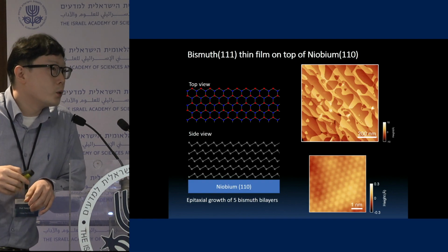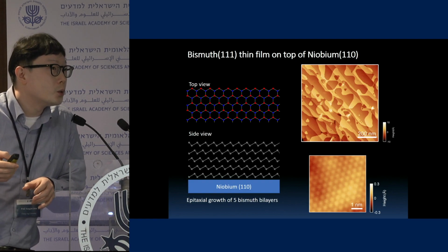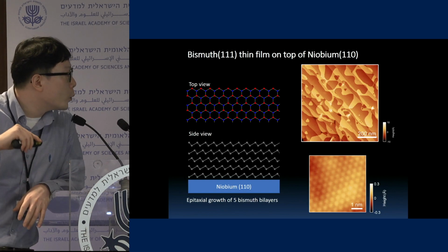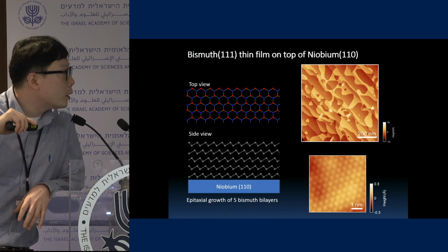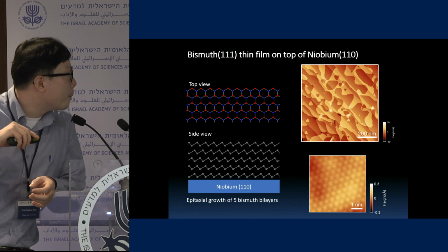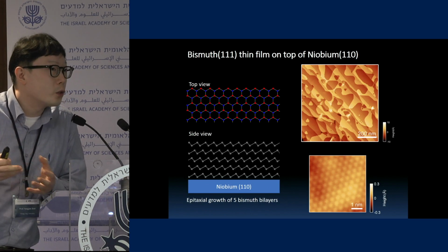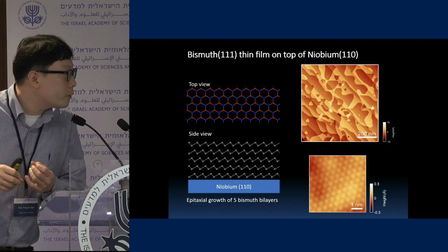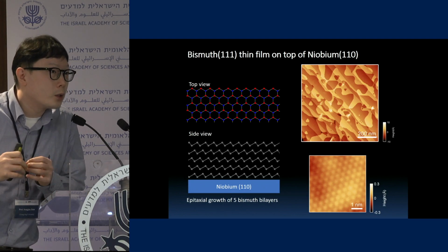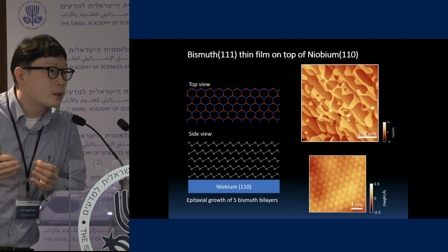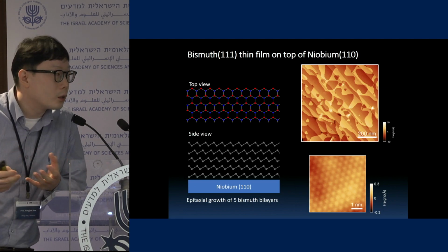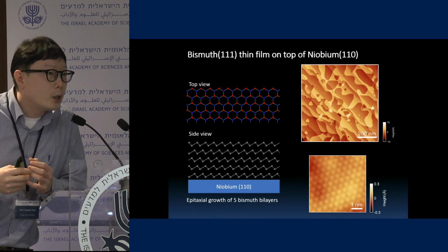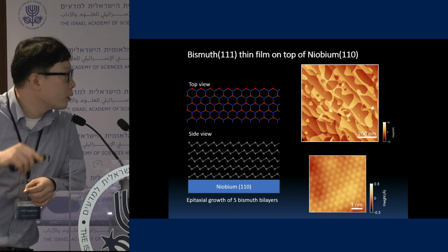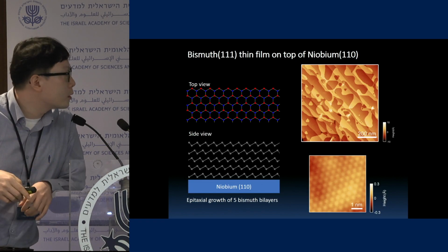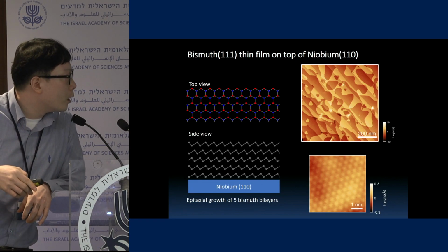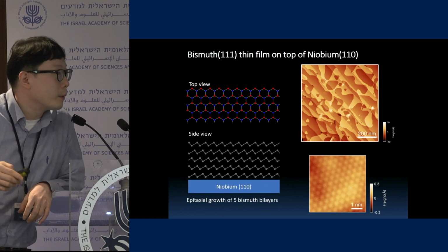So we decided to induce superconductivity in these bismuth systems. We used niobium as a substrate, and we made a thin film of bismuth on it. Actually, we use 4 to 5 layers of bismuth. The reason is that if it is too thin, then it will not grow in one direction, so it will not give us this kind of special edge states. If it is too thick, then it will not get strong enough superconductivity from the niobium. So in our experience, 4 to 5 layers give us a good system to understand the Majorana states.